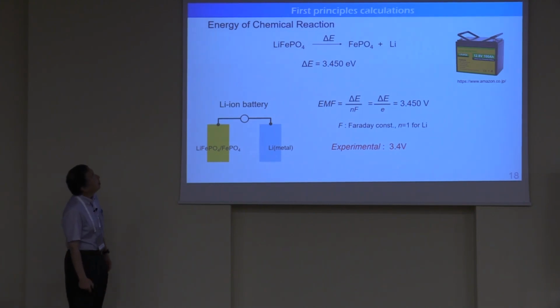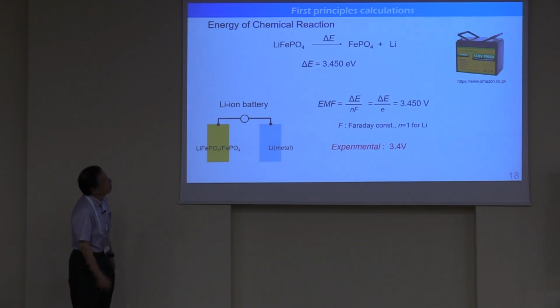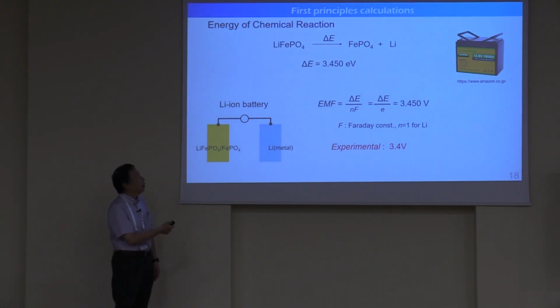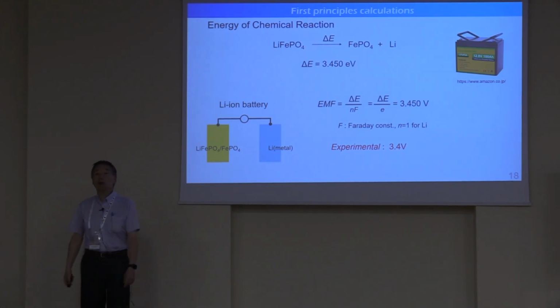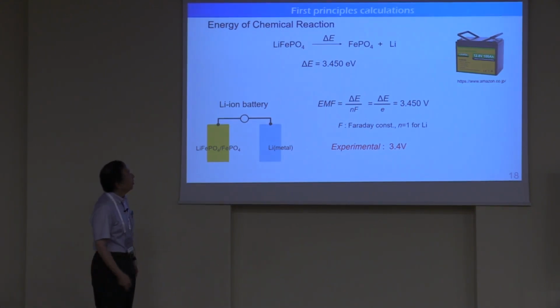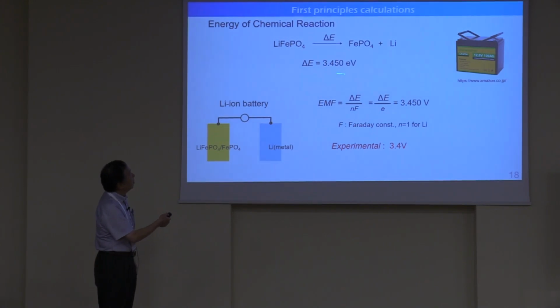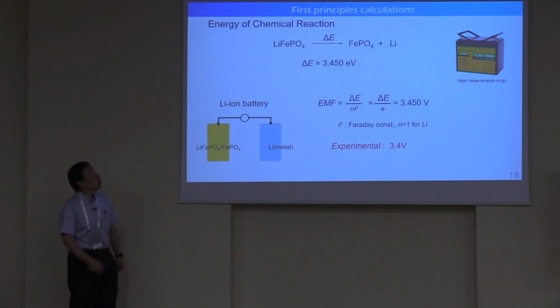In the experiment, if you construct this type of lithium battery, and the electromotive force is expressed like this, putting in the Faraday constant, then experimentally, for this reaction, it is 3.4 volt. So this is electron volt and this is volt, but it is only equal for this reaction because lithium is +1. So they are in good agreement.